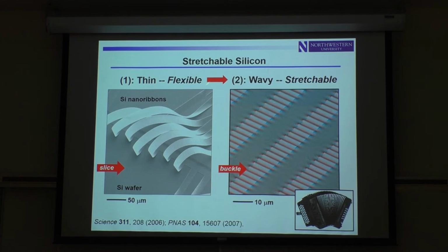But flexible is not good enough for biointegration, because if you think about a flexible device, like on a sheet of plastic, you can bend it so you can conform to simple geometric shapes like cylinders and cones, but you can't do spheres without introducing folds and kinks. And you certainly can't do brains or hearts. You need something that not only bends, but also stretches, in the sense that it supports an elastic mechanics to large strain deformation. And there's no thickness that you can take silicon to that will create a stretchable mechanics. It requires a separate idea and a composite material approach, as illustrated here.